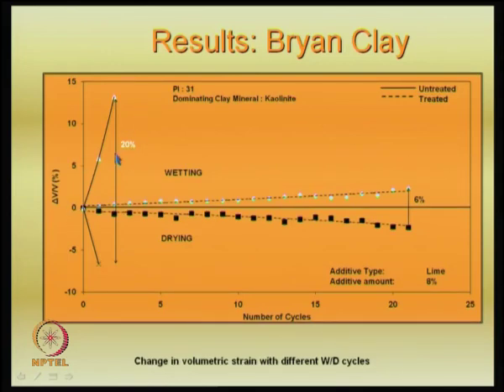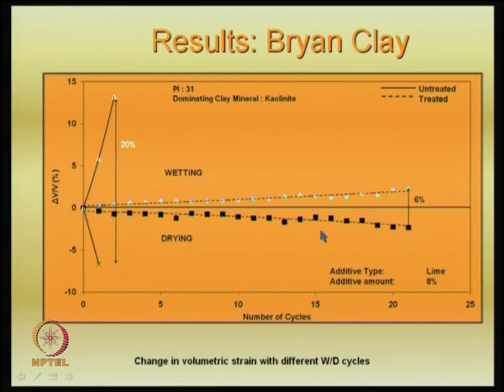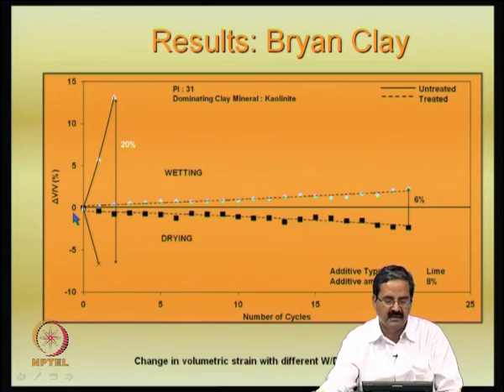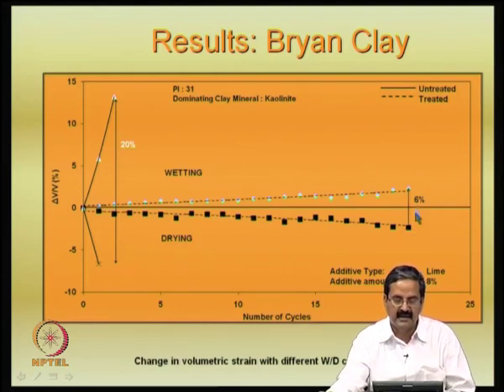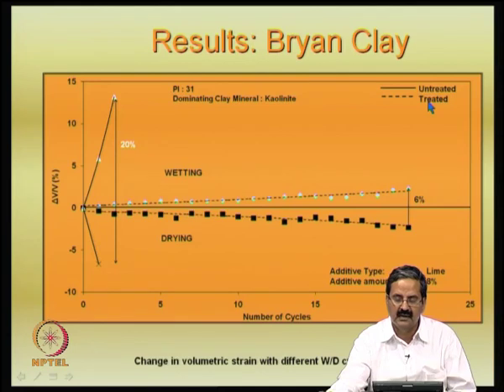Looking at the volume change response: with addition of 8 percent lime and dominant kaolinite with a plasticity index of 31, during wetting and drying the volume change has come down over 21 cycles of testing. You can see that the untreated material has a volume change of about 20 percent (expansion and shrinkage), whereas the treated material shows only about 6 percent change. The treated material is able to withstand more variations because of the minimum change in water content.